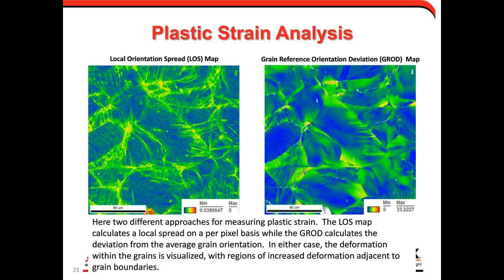We can also compare that to what we call our grain reference orientation deviation, or GROD map. In this map, we calculate the average orientation of a grain, and then for every pixel within a grain, we calculate the misorientation between that pixel and the average, and we plot that on the color scale. You can see in that case, the color scale goes clear up to 33 degrees. So there's a point within the grain that is 33 degrees away from the average orientation. There can be quite a bit of bending present in some of these grains, but we can visualize where this plastic deformation occurs. We can see where it is relative to different grain boundaries or triple junctions within the microstructure.